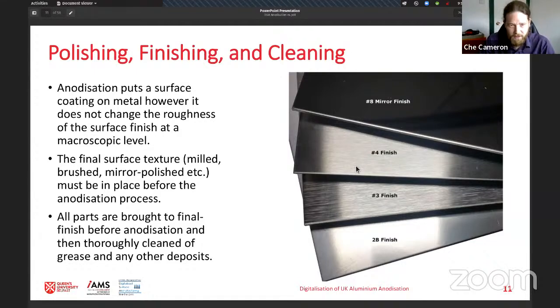So we'll start with the very first part, which is to note that anodization does put this surface coating on a metal, this protective oxide, but it does not change the roughness at a macroscopic level. That means whatever texture you want on your final part, be it milled, brushed, or mirror polished, needs to be in place before the part enters the anodization line. That has a few implications: you have to handle the parts carefully and have good logistics around transportation. But the upshot is all parts must be brought to their final finish before anodization begins, and they have to be very, very thoroughly cleaned of any grease or other deposits from manufacture.